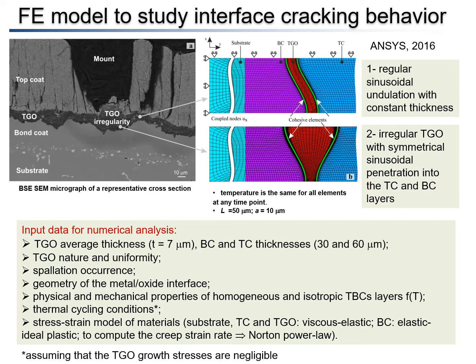The numerical analysis of stress-strain state and cracking behavior was performed using a two-dimensional model for 2 periodic units of thermally grown oxide profile. First of all, it was regular sinusoidal undulation with constant TGO thickness of about 7 micrometers, and the second type is irregular TGO with symmetrical sinusoidal penetration into the TC and BC layers. It was realized based on the representative backscattered electron image of localized penetration.